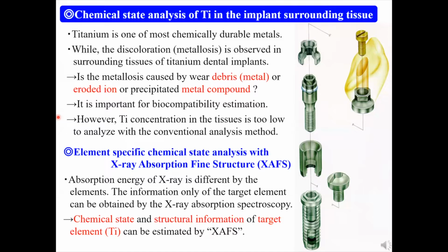In order to estimate the chemical state, X-ray diffraction, XRD, or X-ray photoelectron spectroscopy, XPS, are popularly used. However, titanium concentration in the tissues is too low to analyze with those conventional methods. Therefore, we applied X-ray absorption spectroscopy with synchrotron radiated X-ray, called XAFS.